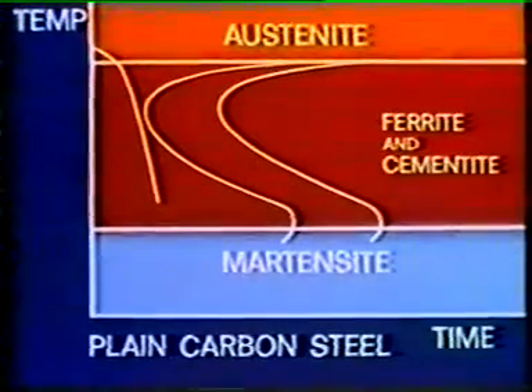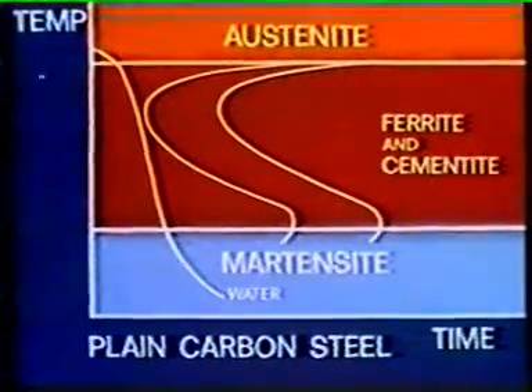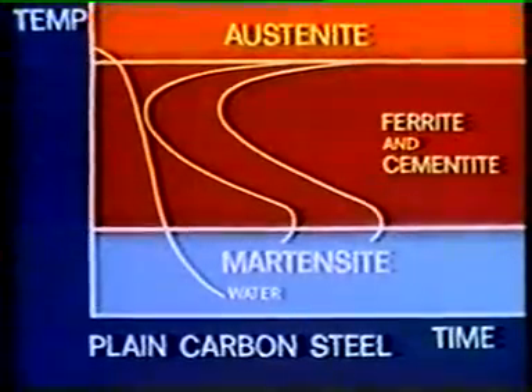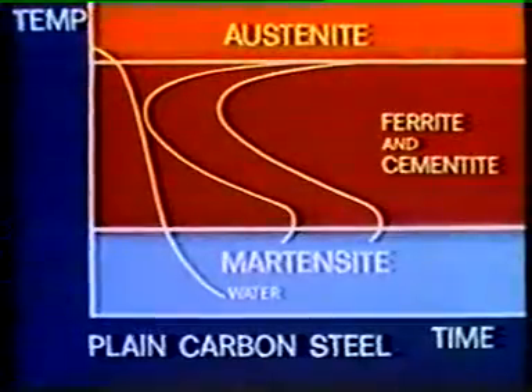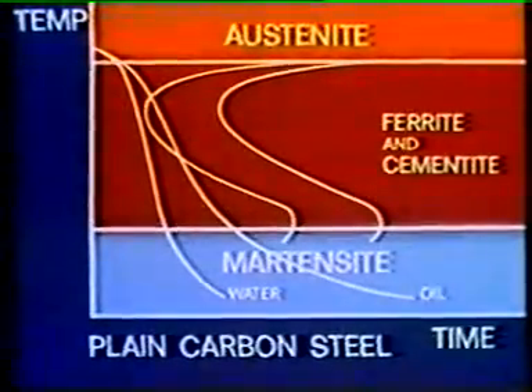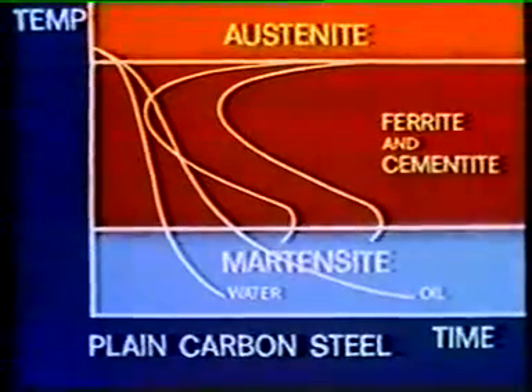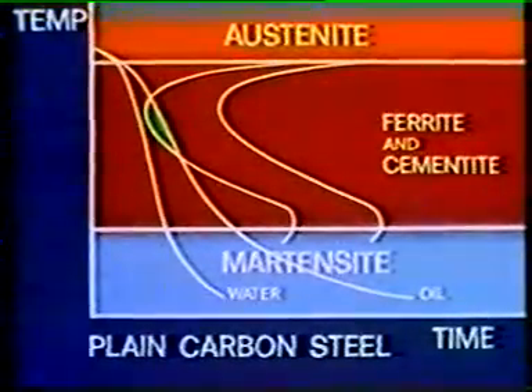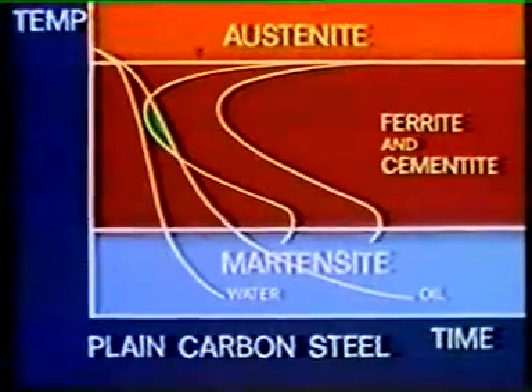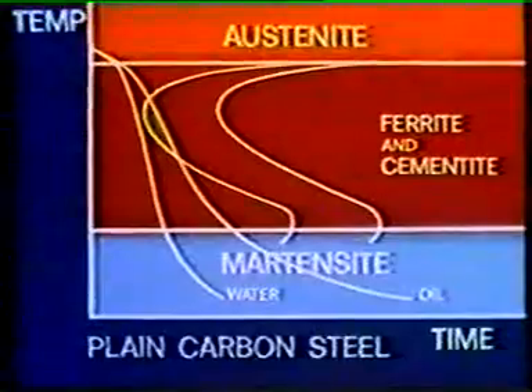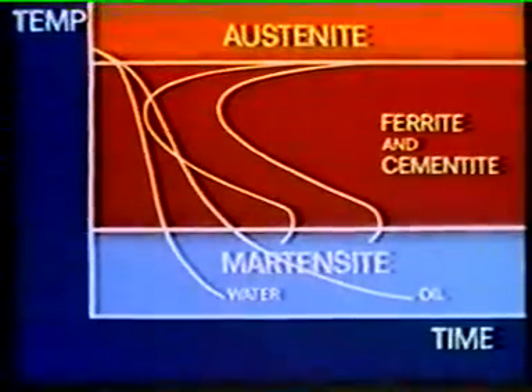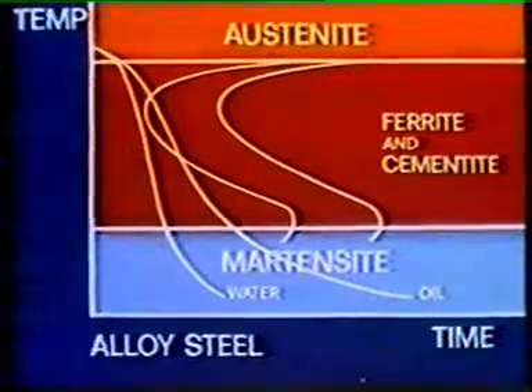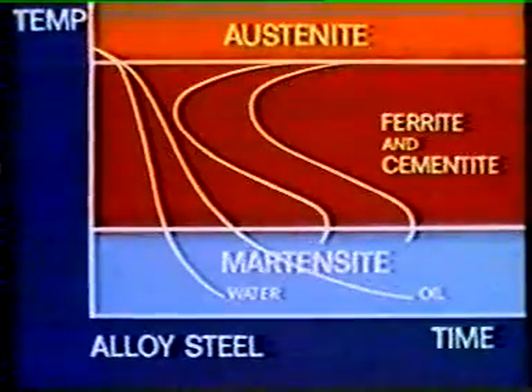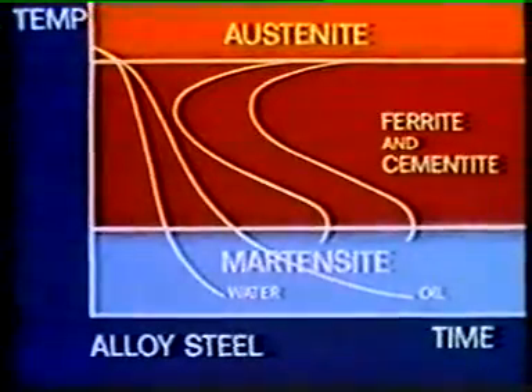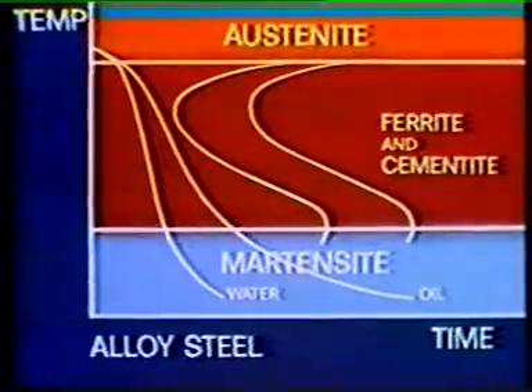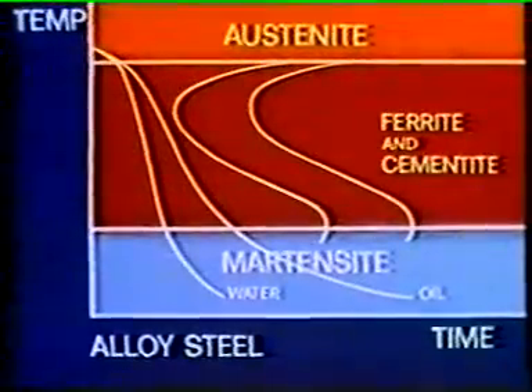Cooling in water is so rapid that there's never time for unwanted transformations. But when we plot the slower cooling rate of oil, we see that between about 600 degrees and 500 degrees, some transformation into ferrite and cementite takes place, though it will not be completed. Only what remains of the original austenite will harden. Now suppose the same experiments are conducted with an alloy steel instead of a plain carbon steel. The transformation times are retarded, as you see, so the alloy steel can be quenched in oil, thereby avoiding the possibility of cracking or distortion, and without unwanted transformations.